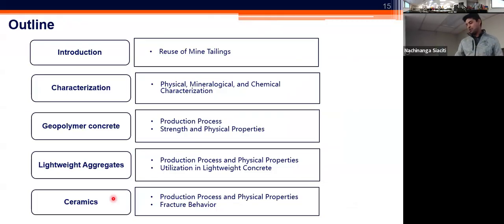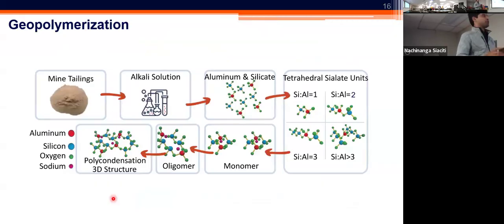So we need to put a little bit of a chemistry hat on so we can go through this, but I try to simplify this process. The geopolymerization process involves the use of the precursor or the feedstock, in our case the mine tailings, as material subjected to a fairly high pH, alkali-rich environment, usually with exposure to solutions like sodium silicate and sodium hydroxide, and the mixture of the two, you can facilitate the release of more reactive aluminum